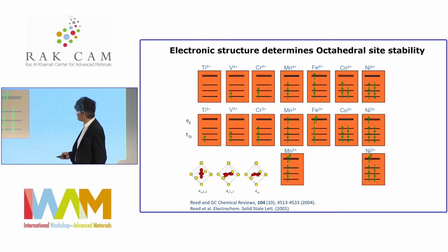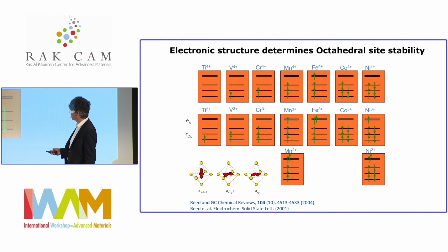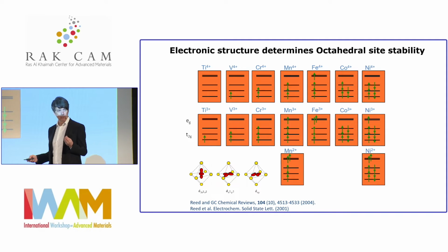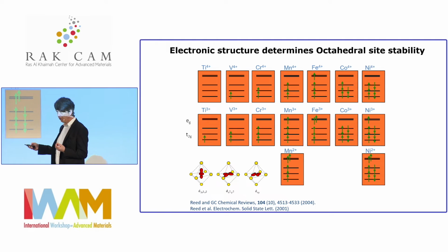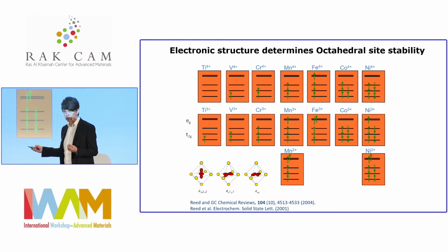You look at ligand field splitting of the d orbitals, and roughly here's a cartoon. The 5 d orbitals are split, 3 down and 2 up, right? These are the ones with T2g symmetry. These are the ones with eg symmetry. So to be stable in an octahedral environment, you need to fill the lower ones and not the upper ones, essentially.